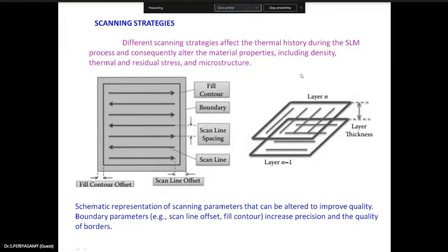The circle, then neck forming, then it goes for coalescing, then you have a layer. If the layer is not formed, that is what happens. If it is a circle, at the top you have enough gap, at the bottom you have enough gap. So there is a possibility of increasing the porosity. Similarly, the roughness. If you have micro level features that are not coalescing, you have a roughness.